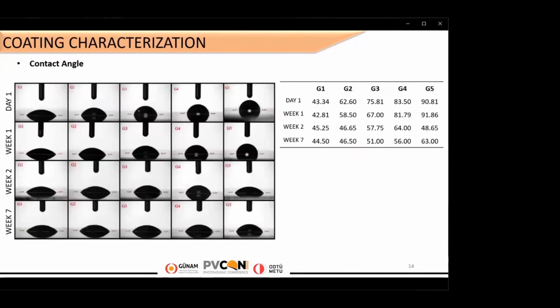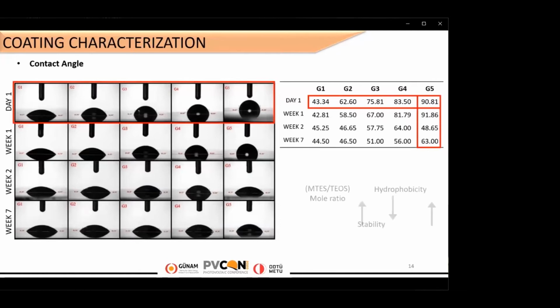You can see droplet images in here and contact angle values of all coatings. Columns represent solution versions with different MTES, TEOS ratios, and rows represent coating times. We can say that the hydrophobicity of the surface is increasing with increasing MTES content. It can be thought that this is due to the organic group increase. On the other hand, the stability of the G5 solution is lower than the others.